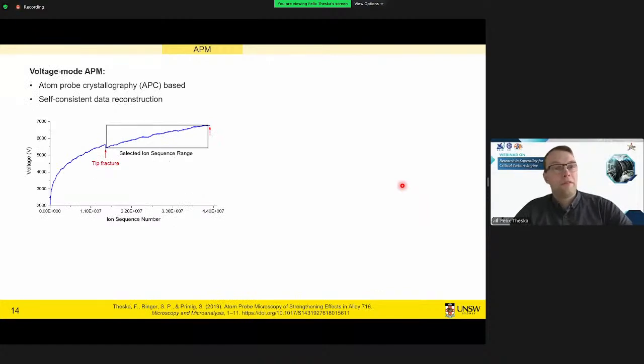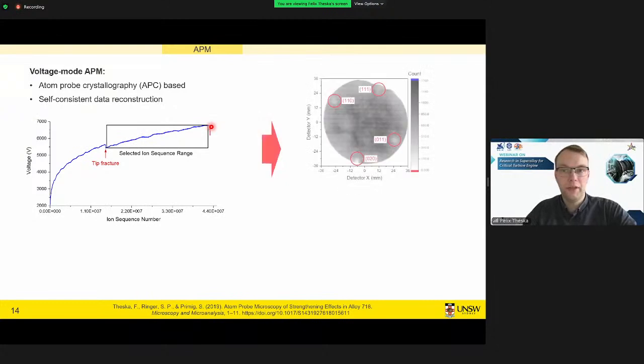Okay, so starting with voltage mode Atomprobe microscopy, that means we detach atoms by voltage pulsing. We can exploit crystallographic features in the data, and that's then called Atomprobe crystallography, a whole different research topic. But we start the reconstruction with such a voltage curve. You see on the bottom the ion sequence number, which tells us the number of each ion and the voltage it evaporated at. And you see the very first atoms to evaporate took very little voltage, but then the tip becomes more blunt and we need a higher voltage. So we avoid any tip fracture and then have a look at what the detector has seen.